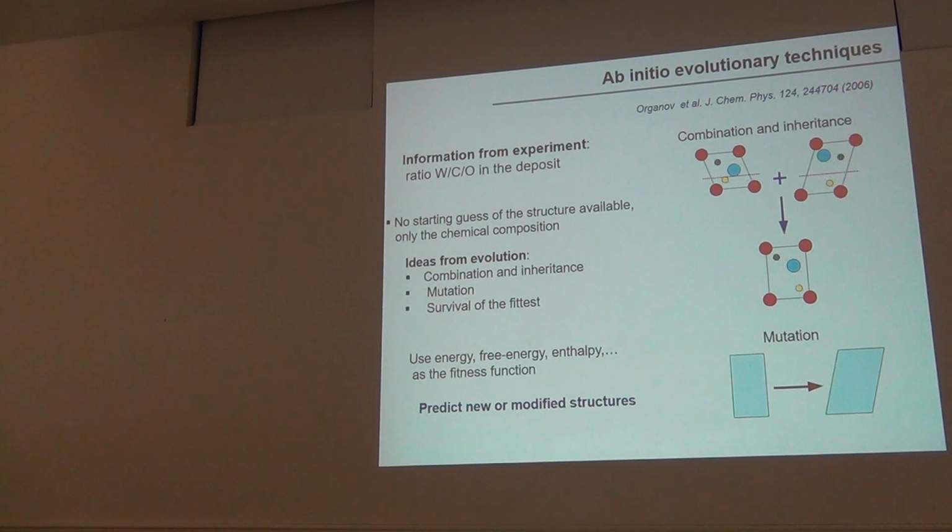Here I should mention one thing. Density functional theory calculation, I had it in my slide, but I didn't say it, follows the variational principle. So when you calculate energies with density functional theory, these are variational energies. So one thing that you really know is you can use all the properties of the variational principle. Your energies for the wave functions, the basis set that you chose, this is the best energy that you have. Therefore, that's why we can use DFT in combination with a genetic algorithm in order to find the fittest or the optimal structure where we start with for our calculations.